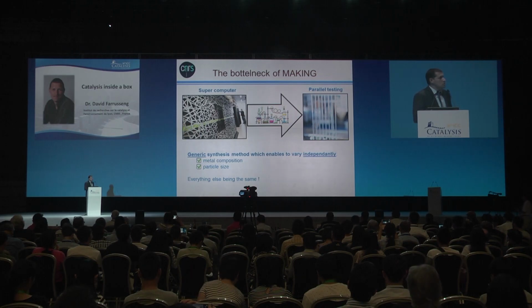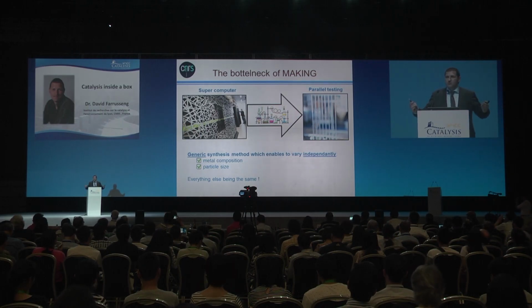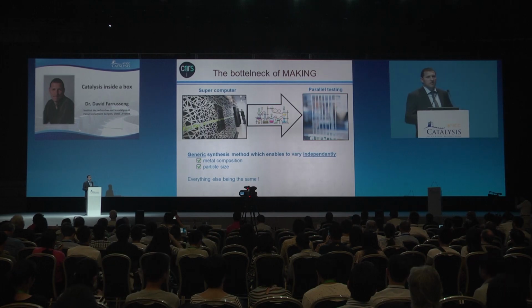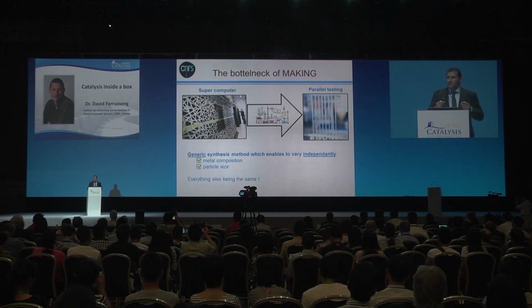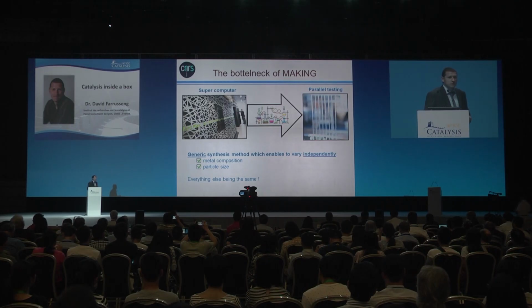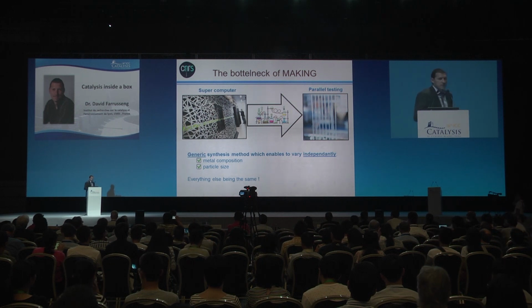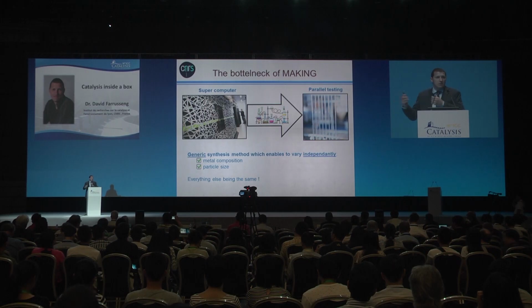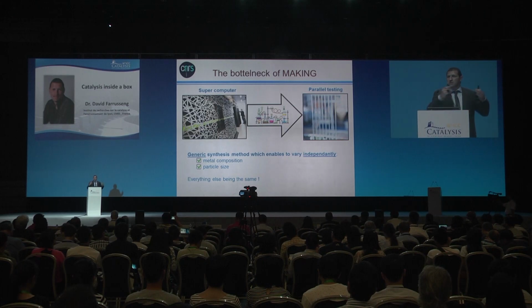It's no longer an issue for testing either. We have parallel tools. We can test bunches of catalysts in a couple of hours or days. The bottleneck is actually to make the catalyst with a high control of the surface composition and particle size. For example, we could fix the metal composition, like 50% gold, 50% silver, and vary the particle size, or fix the particle size, say 8 nanometers, and have many different bimetallics of different compositions at this particular size.